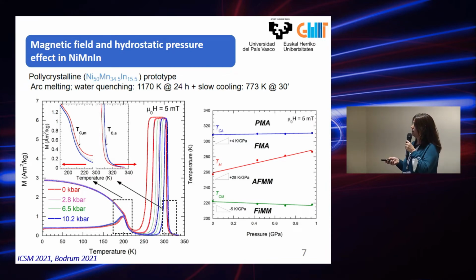And it seems that the impact of this pressure, hydrostatic pressure, on the structural transition is higher than in the case of the magnetic one.